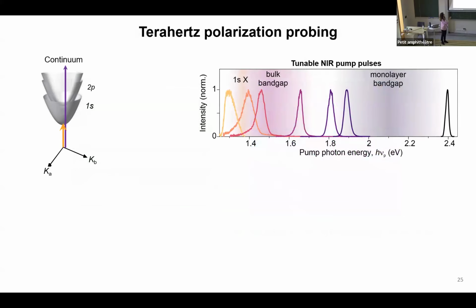What is the idea behind terahertz polarization nanoscopy? The rule of the game is the same. We have to first generate the excitons to be able to study them, right? So we generate them with some near-infrared radiation. For this specific project, we use different excitation pulses whose spectra are shown here. Just for comparison, I showed you where the 1s exciton recombination peak should lie, where the bulk band gap should be, and also the region where the monolayer band gap has been reported so far. So with our pump pulses, we are going through all of these regions, and we can gain a lot of useful information, as I will show you shortly.